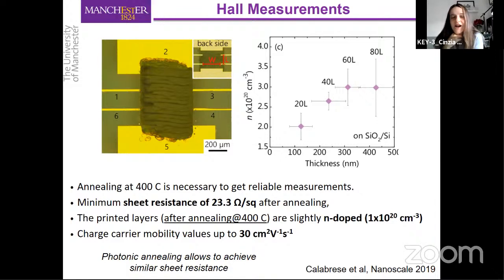And at such a high temperature, all the additives that we use are basically boiling, so they should not be present anymore. Just the pyrene is boiling at around 400 degrees C. So maybe some pyrene will be left at that temperature, but most of the additives will be gone. And indeed, the sheet resistance dramatically dropped, and we were able to achieve around 20-30 ohm per square.